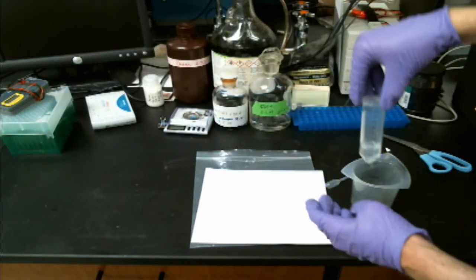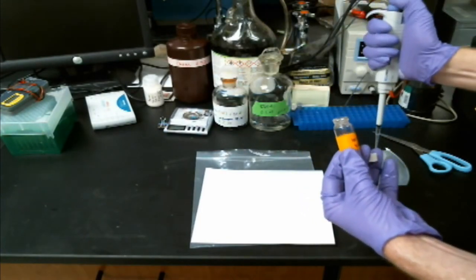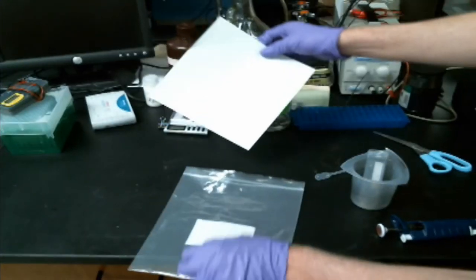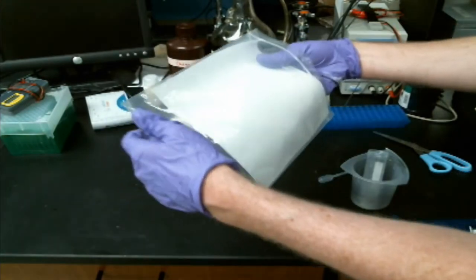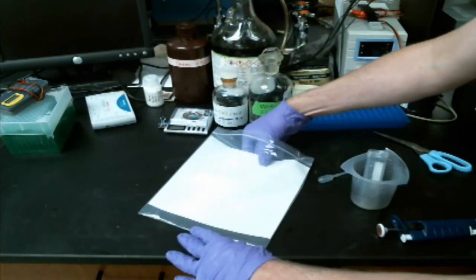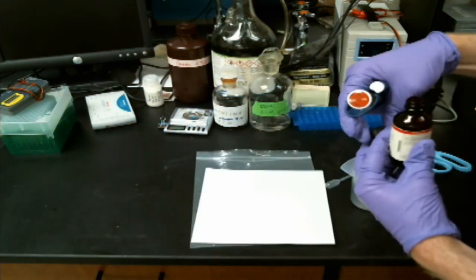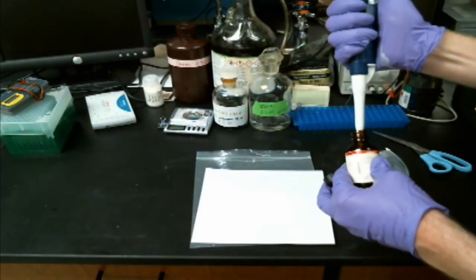So now I've got water, bisacrylamide, acrylamide, and acrylic acid. I'm going to add some ammonium persulfate to that, about 40 microliters of 10% ammonium persulfate to 10 mils of total solution, and then put my paper spacer inside my bag.